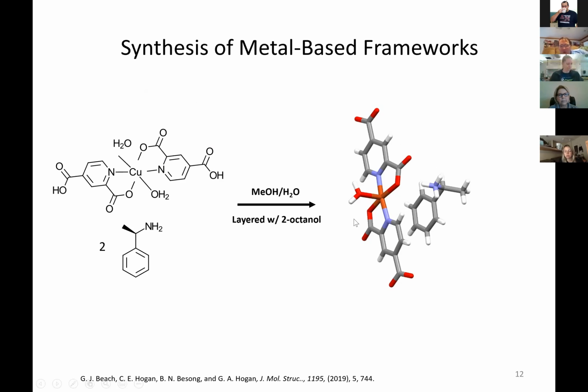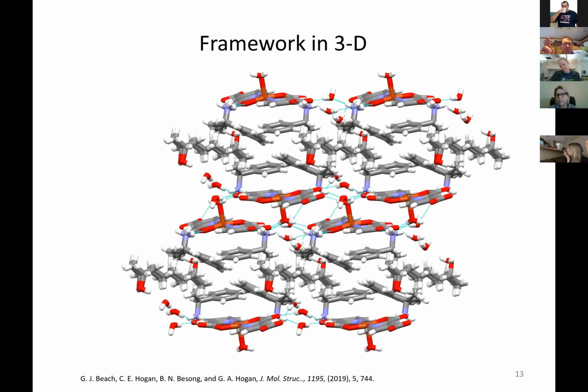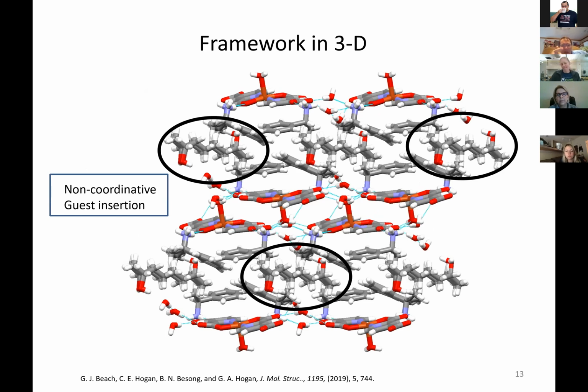It actually crystallized very beautifully. It was one of those crystals I showed you on one of the first slides with the 4 crystal vials. We got the exact same unit cell, which is good reproducibility. Grow it in 3 dimensions and it looks a little different. The difference is that now we actually have a guest inclusion inside our framework. This is what we call non-coordinative, meaning it hasn't bonded to the metal itself. That's good. We still have the bilayer, as you can see right here in this middle section, but we have now included our 2-octanol molecule.